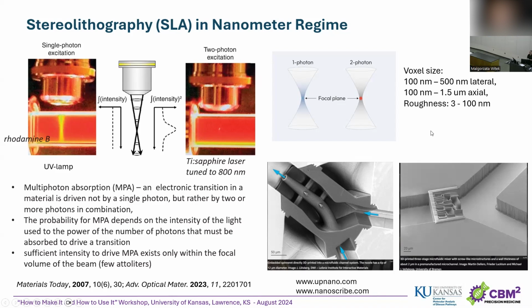The minimum resolution, the voxel size, I forgot to mention. A voxel is a pixel in 3D printing. Everybody knows pixels from screen resolution or printer resolution, but a pixel is 2D, just a little square. A voxel is a volumetric pixel, so it's really 3D: the smallest volume of your 3D built part. With 2-photon polymerization, we can go down to 100 to 500 nanometers lateral and 100 nanometers to 1.5 micrometers axial in size. And I believe that's it.